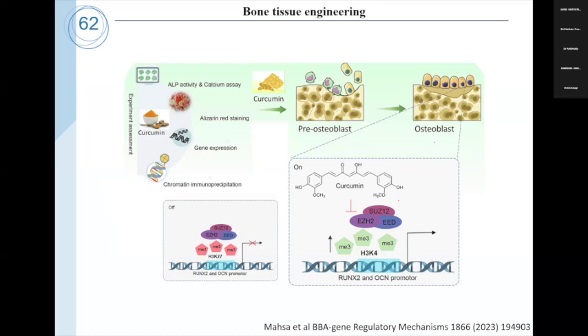Typically, when a bone is affected by disease such as cancer, various inhibitors such as enhancer of zeste homolog 2 (EZH2) are produced, which interfere with bone formation. We found that expression of the EZH2 gene was down-regulated in the presence of curcumin during bone formation. To put it simply, it is not easy for new bone to form in diseased bones such as cancer. This is due to the EZH2 gene, which prevents the formation of new bone. Because curcumin inhibits the expression of EZH2, curcumin helps in bone formation.